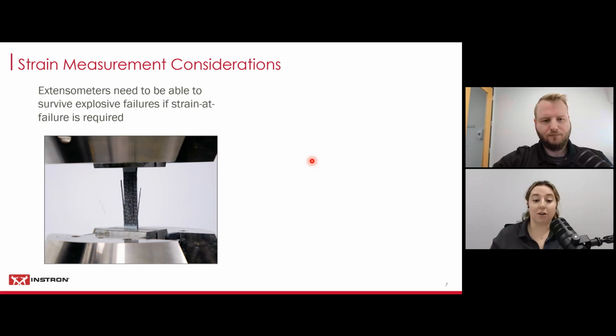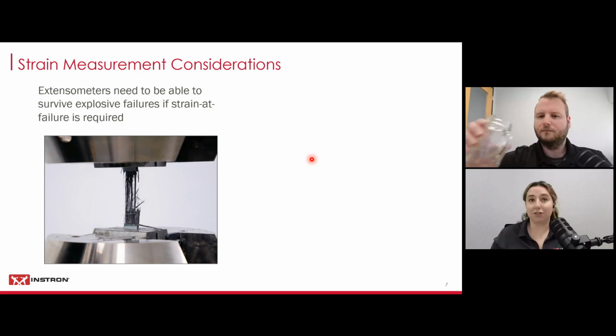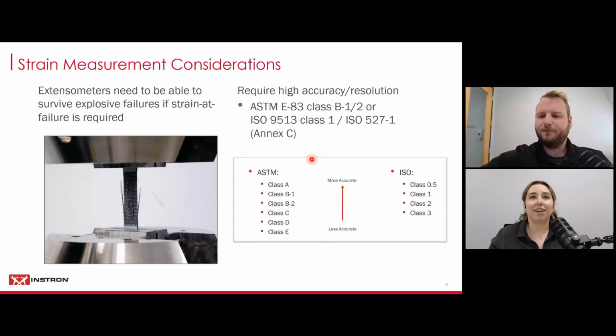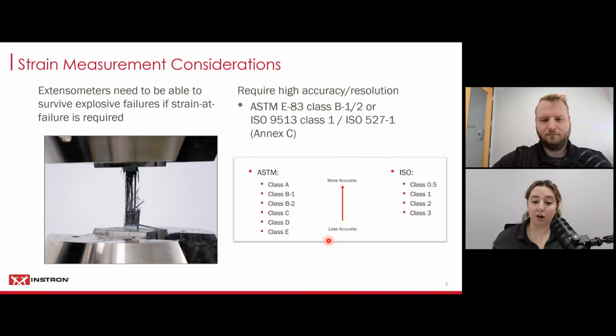So to kick things off, let's talk about some typical strain measurement considerations, such as what Stefan showed, just reiterating. Extensometers need to be able to survive explosive failures if strain at failure is required for your testing. And then most importantly, the strain measurement solutions need to be able to meet the requirements of the appropriate strain measurement standards. So that requires high accuracy and resolution to ASTM E83 classes B1 or B2, or ISO 9513 class 1/ISO 527-1 Annex C. And the graphic that we're showing here shows the different ASTM and ISO classes from least strict on accuracy on the bottom to most strict.